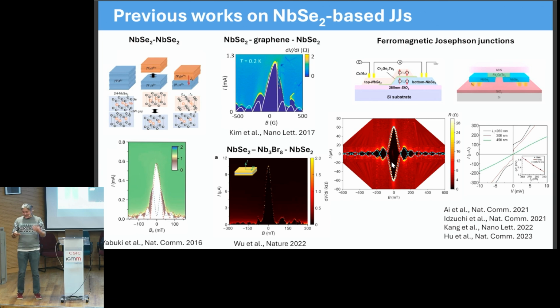To later compare to our results, I just wanted to flash also a typical characterization measurement that we do with Josephson junctions, which is to apply a magnetic field perpendicular to the flow of the supercurrent and see the interference pattern. So usually in a Josephson junction that has a homogeneous distribution of supercurrent, you would get a pattern that is known as a Fraunhofer pattern, right? Which looks something like this, or a bit distorted in other cases, but more or less all of these different devices show this kind of pattern.